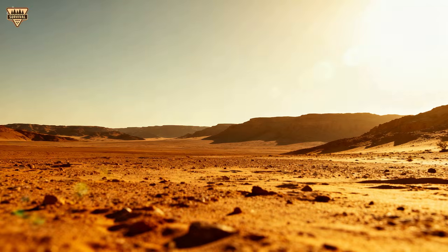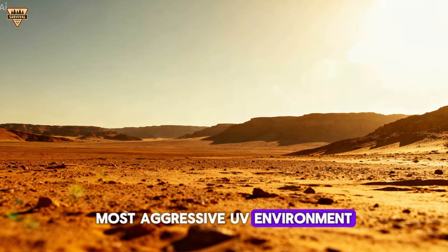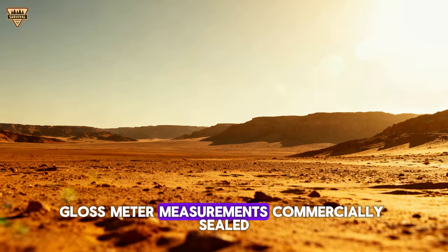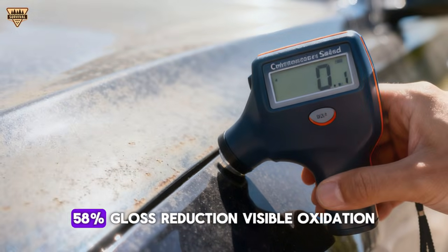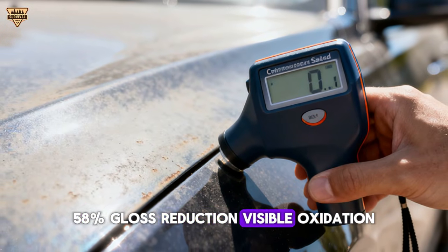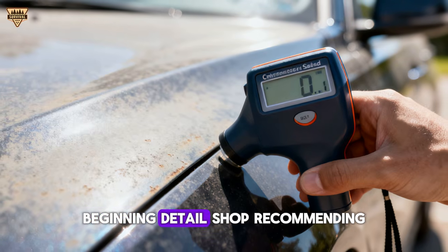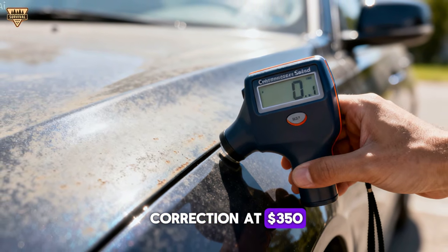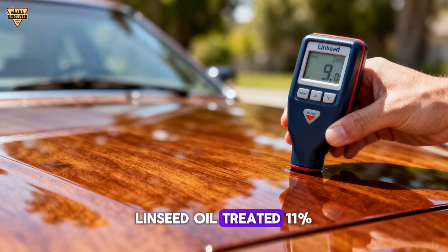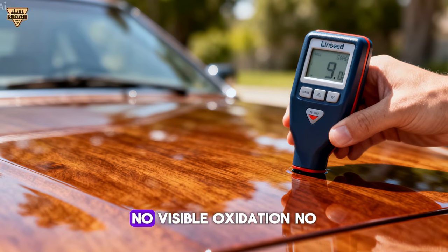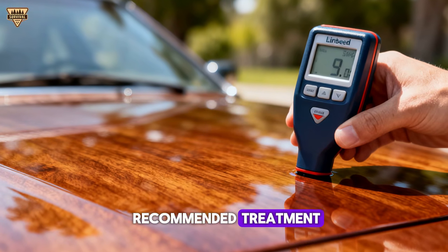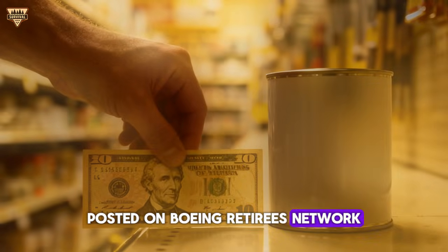After 3 Arizona summers, most aggressive UV environment for automotive paint, gloss meter measurements, commercially sealed: 58% gloss reduction. Visible oxidation, beginning. Detail shop recommending correction at $350. Linseed oil treated, 11% gloss reduction. No visible oxidation, no recommended treatment. Posted on Boeing Retirees Network.